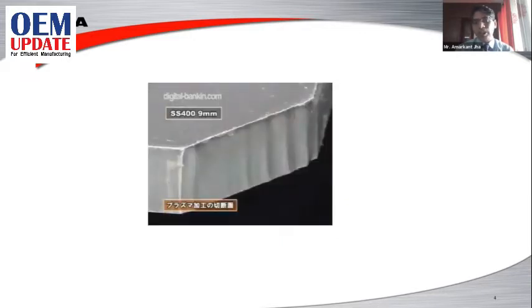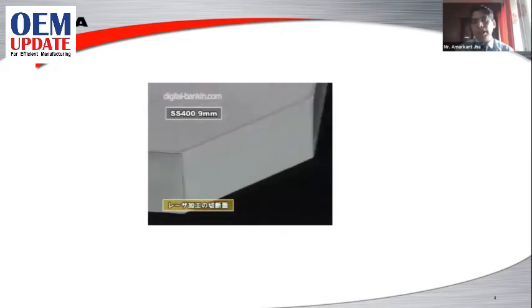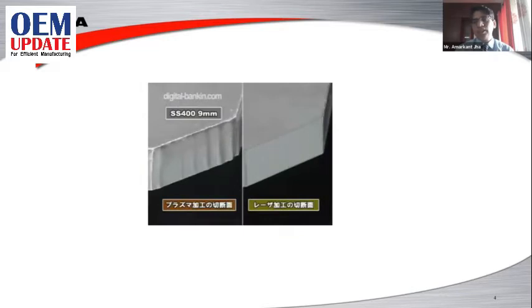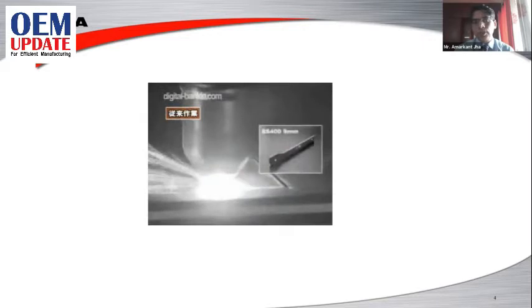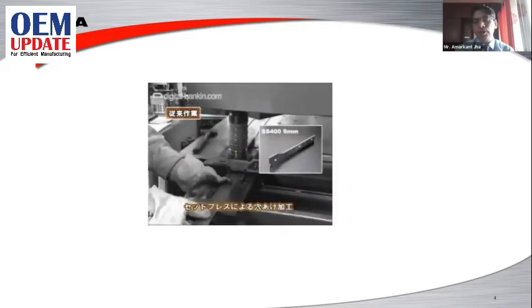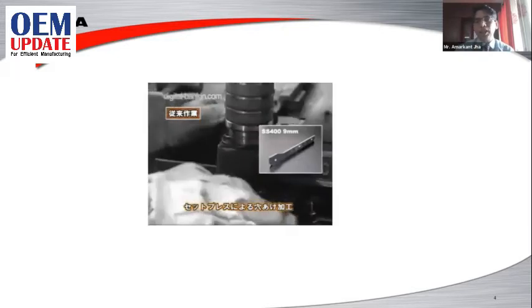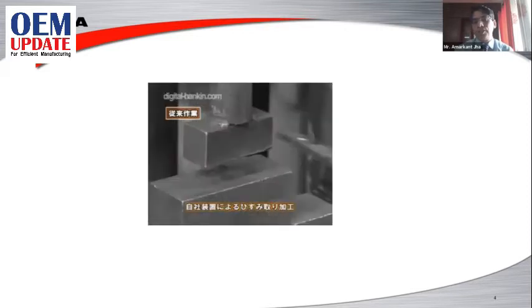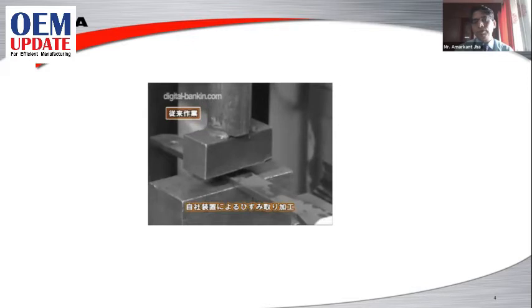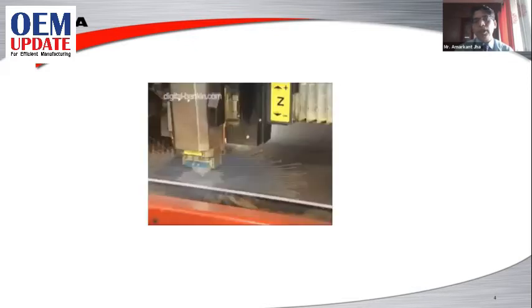Similarly, you can see here the particular job, 9 mm thickness, it was having a substantial amount of taper. When they switched over to laser, this taper was completely eliminated. In case of laser, you can achieve a taper of 0.2, 0.1, even on 25 mm material, you can achieve up to 0.5 taper. This is the secondary process they used to do. After cutting on plasma, they were making small holes on a set press. But in case of laser, this process was eliminated.